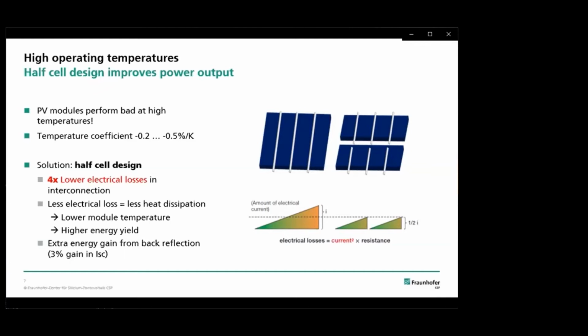And less electrical losses will also mean we have less heat dissipation in our PV module, which will end up in lower module temperature and at the end in a higher energy yield. And in addition, we could also get an extra energy gain from back reflection from the backsheet because we now have a gap between the cells. That this totally makes sense is also shown in the market currently, which moves strongly towards half-cell modules. We proposed it already back in 2016.